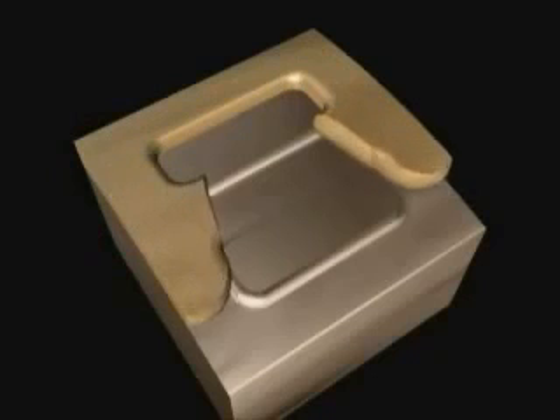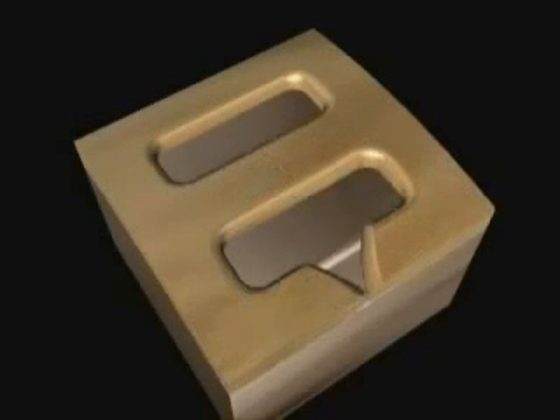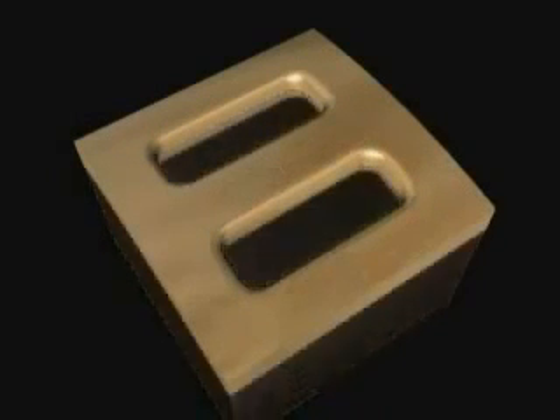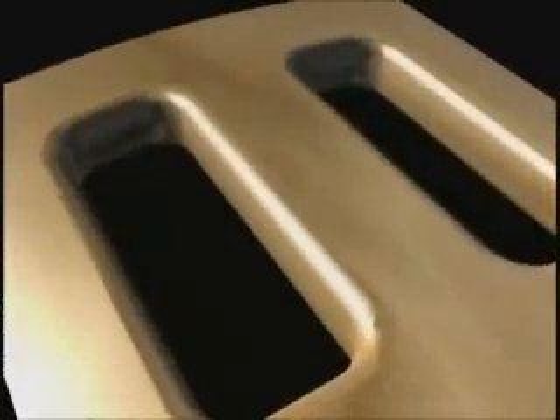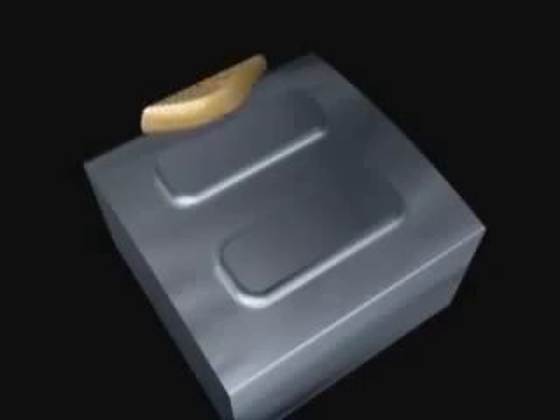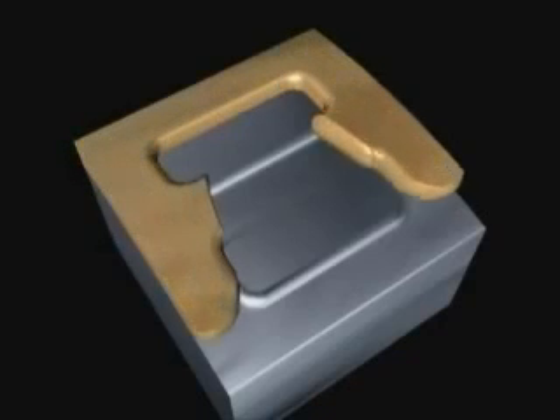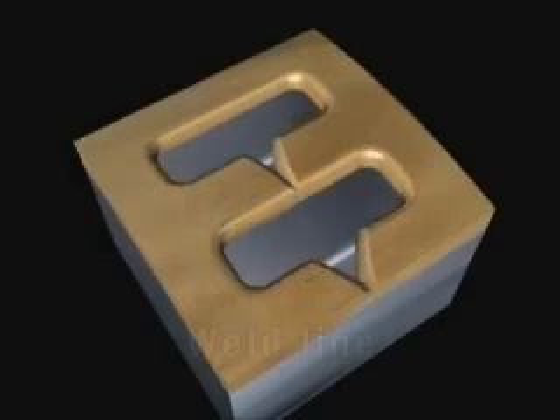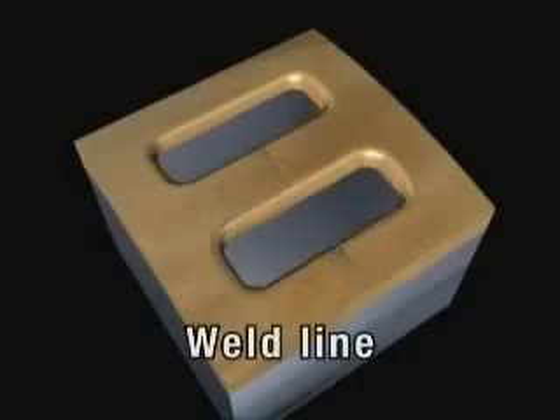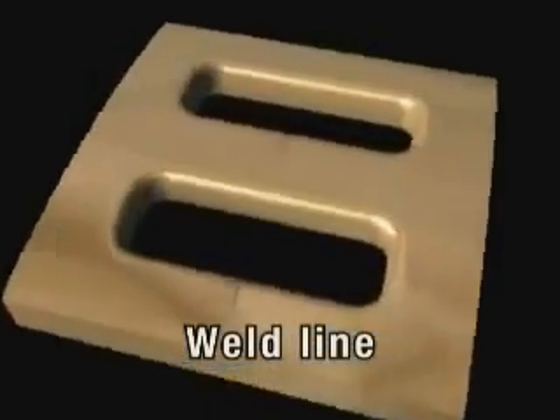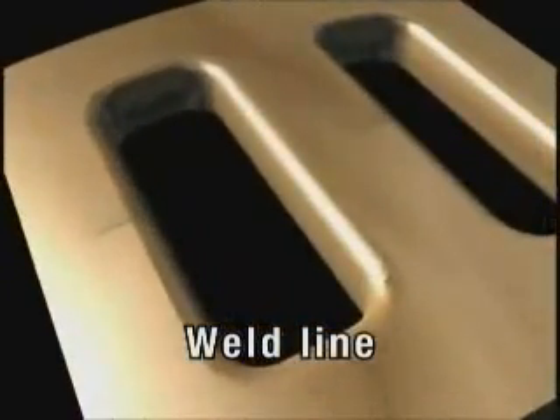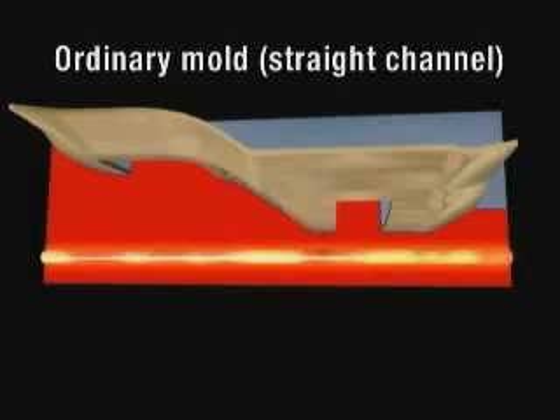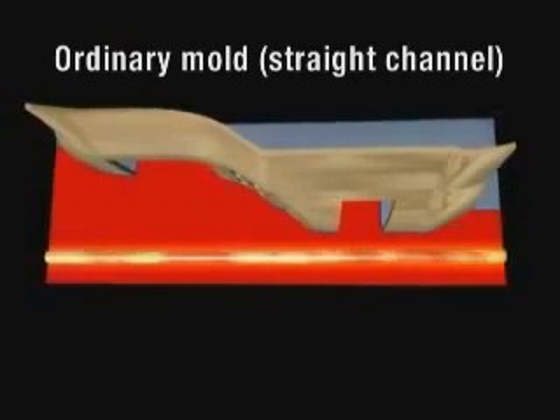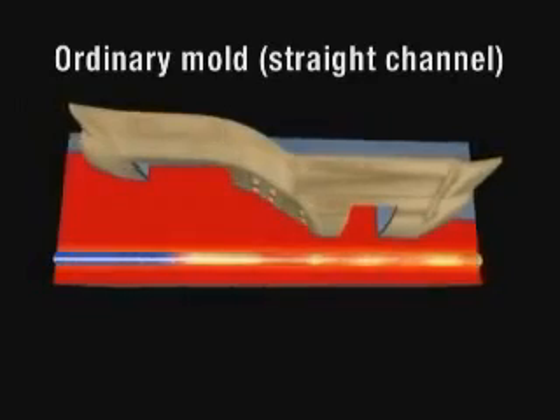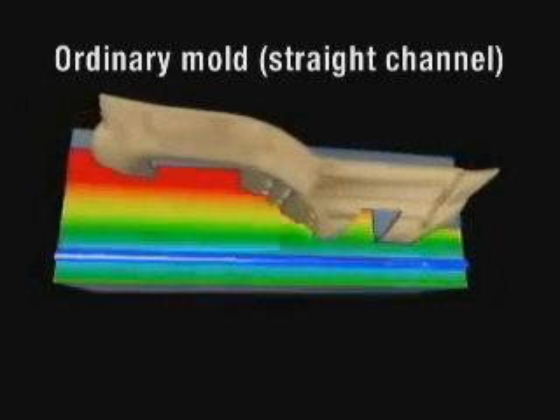For cavity surface temperatures higher than the deformation temperature, the weld lines are not possible because the resin has sufficient fluidity. However, if the cavity surface temperature is low, the resin starts solidifying. Also, the resin does not properly mix and weld lines appear. Even by heating the entire cavity surface to the same temperature, cooling and mold cycle times are prolonged.